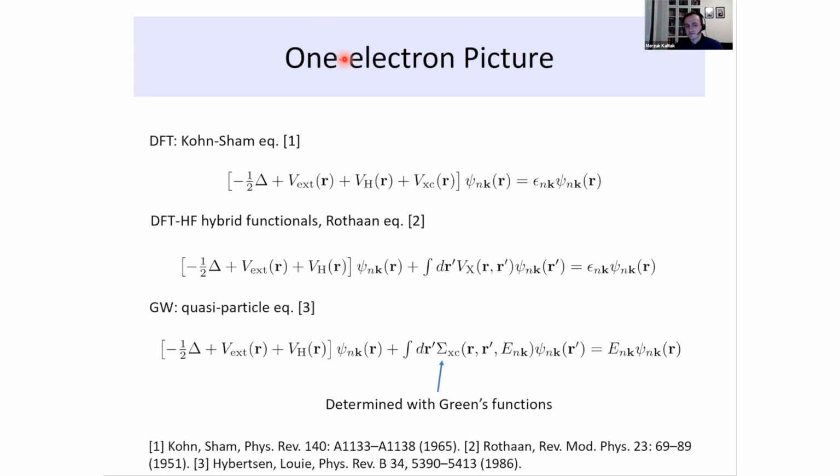The ground state can be done fairly quickly. In VASP, I think you can do up to 1,000 electrons. But if you go further and use hybrid functionals, it's already very costly. With this low scaling GW, if you compute the total energy, we have done calculations for up to 200 atoms in a cell, I think 1 hour on 128 cores. GW is slightly more expensive, so I would probably factor that by a factor of 4 in time. But I think it's doable.